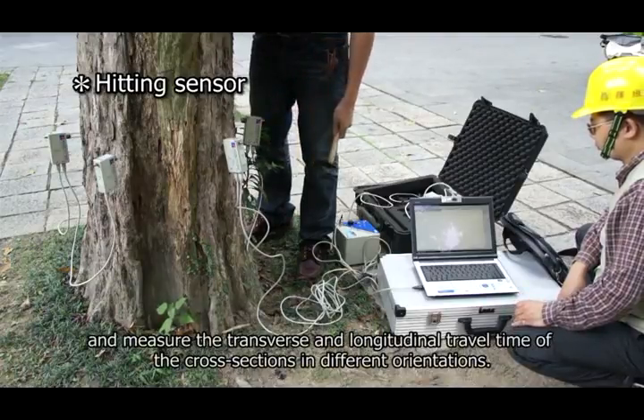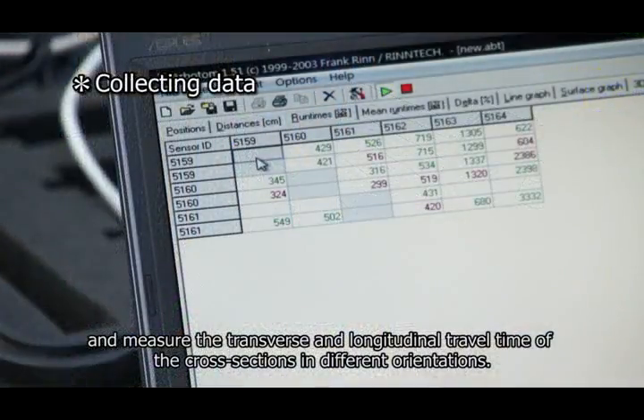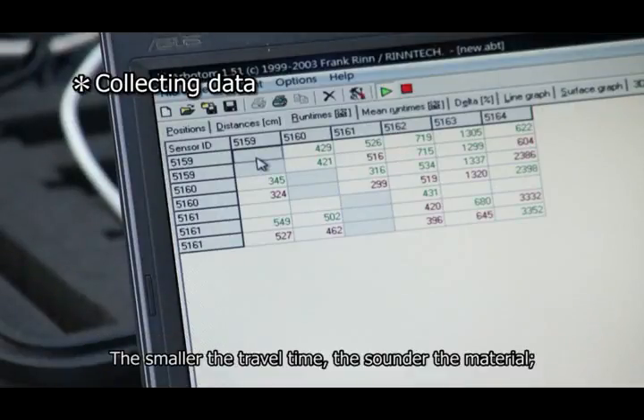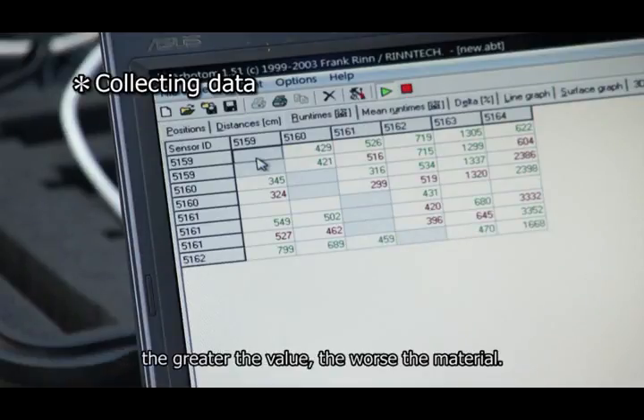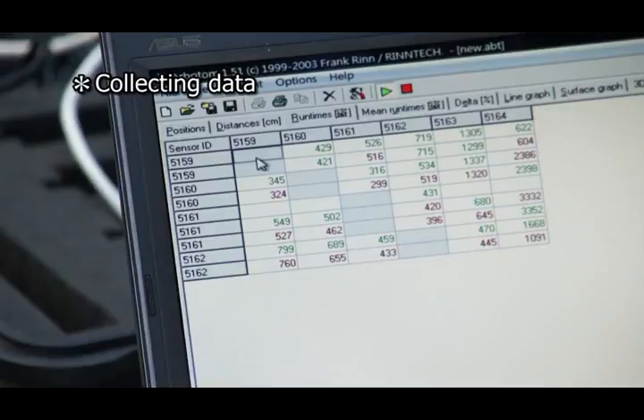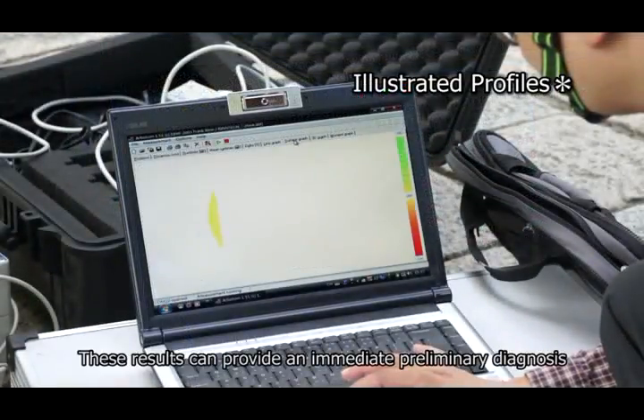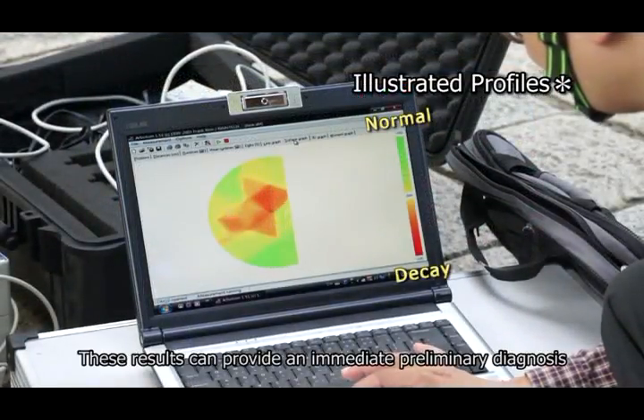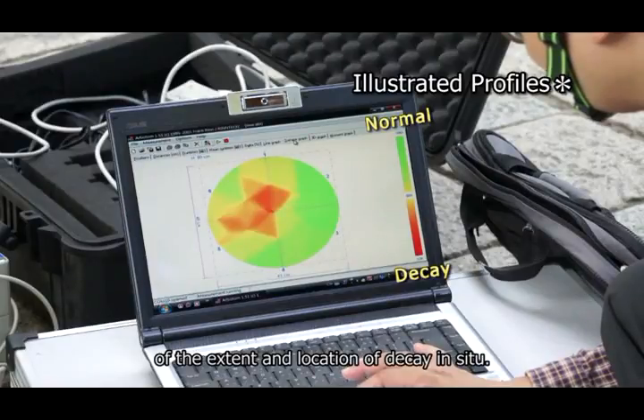and measure the transverse and longitudinal travel time of the cross-sections in different orientations. The smaller the travel time, the sounder the material. The greater the value, the worse the material. These results can provide an immediate preliminary diagnosis of the extent and location of decay in situ.